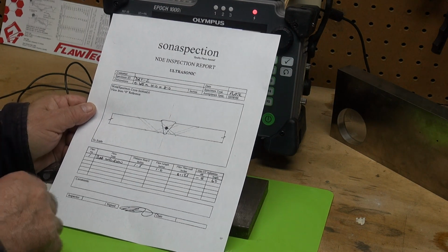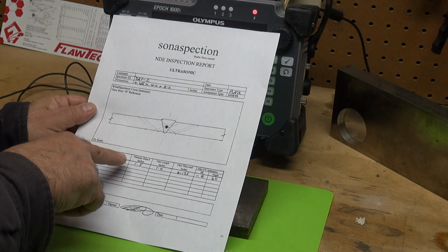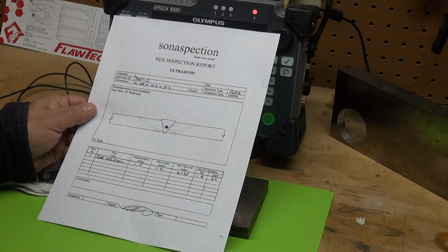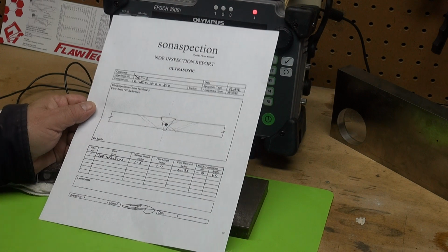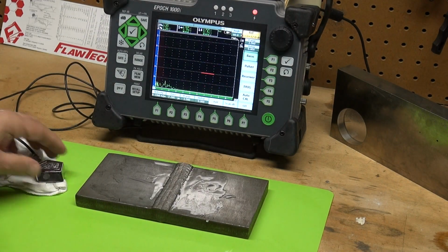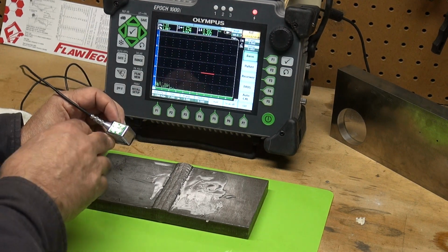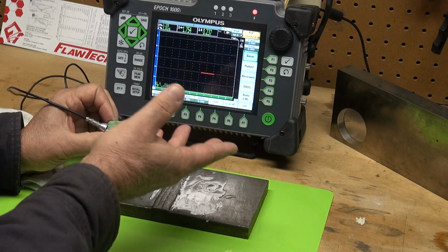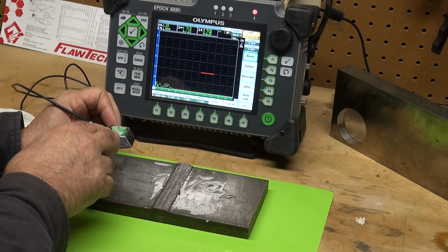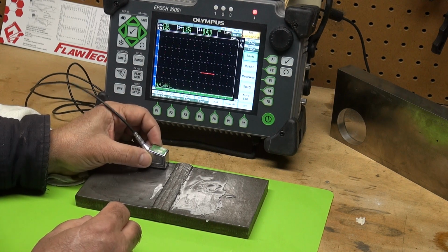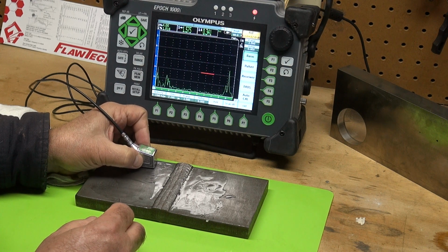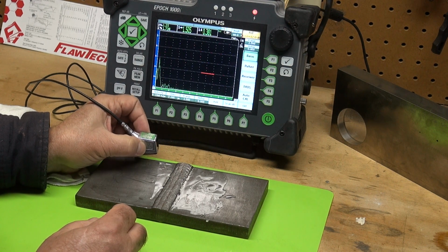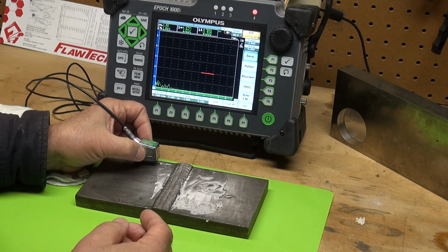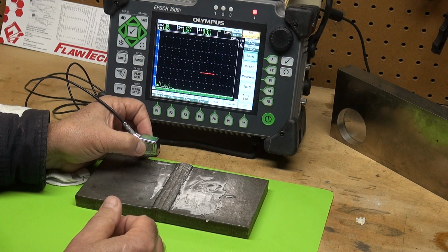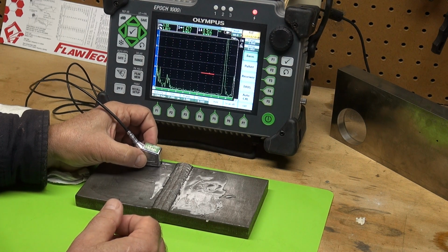It's called slag. So this weld that I have today, the base metal is 0.625 inches thick. And right about in the center line of that weld, we have some slag. So I'm using my Epoch 1000i, and I am using a 60-degree wedge on a 4 megahertz, 10 millimeter diameter transducer, and I calibrated on an IIW block. My reference gain is set at 63.8 dB. I used the 0.6 deep side drilled hole on my IIW block as my reference.